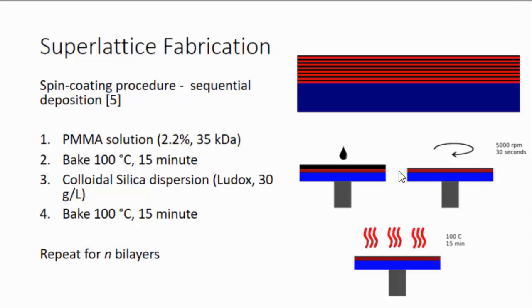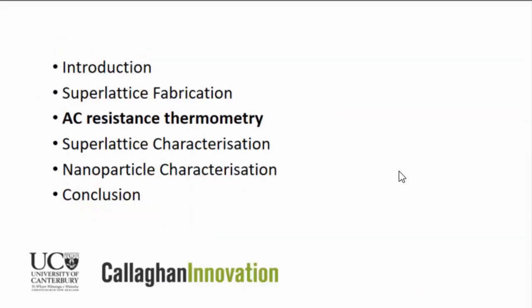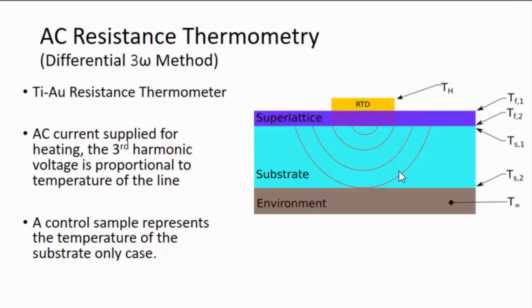So now I'll talk about the technique that I used to measure this material, which was AC resistance thermometry. The basis of this technique is we fabricate a titanium gold resistance thermometer on the surface of our superlattice crystal. By then applying an AC current through it, we're able to create thermal waves which penetrate through the material. And then by monitoring the third harmonic of our electrical driving frequency, we can monitor the temperature at the surface of our superlattice. By then comparing that to a control sample, you can isolate what the effect on the thermal conduction of the superlattice structure alone is, and therefore work backwards to the thermal conductivity and the thermal diffusivity, if you wish.